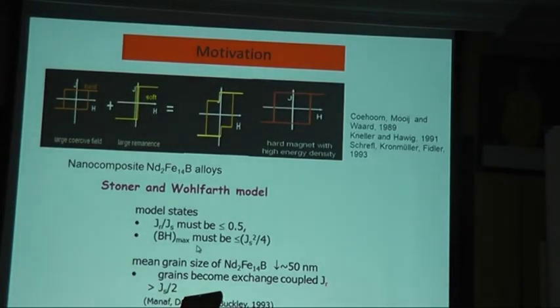Next, this is the motivation for nanocomposite NdFeB. It's a combination of large coercive field and large remanence. Hard NdFeB has very high magnetocrystalline anisotropy. For completely exchange coupled magnets we get a square hysteresis loop, or we can get a kink in the second quadrant, which shows that it's not completely exchange coupled. From the Stoner-Wohlfarth model, the remanence ratio must be less than 0.5. But if we decrease the size below 50 nanometer, we can get more than 0.5. That's the value that we are trying to achieve.